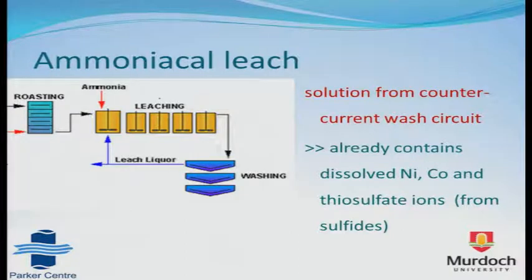When this reduced material is fed to the leaching tank, it comes into contact with the solution which already contains dissolved nickel, cobalt and thiosulfate ions. The thiosulfate derives from the leaching of the sulfides, because the solution is recycled from the countercurrent washing circuit into the first of the tanks. What's important is the contact of these metals with solutions that already contain these dissolved metals and thiosulfate species, and any interactions that might take place between the solid and the solution.